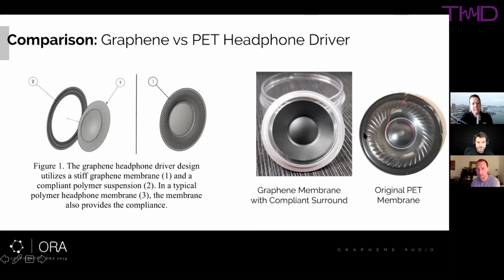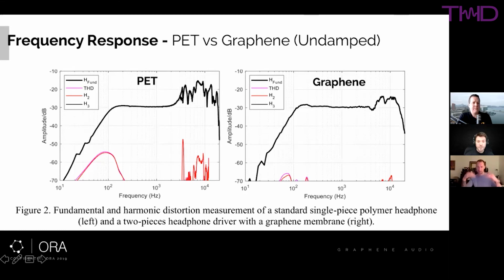So for this, we took a 50 millimeter driver that used a PET membrane and replaced it with our graphene diaphragm. And what we see is pretty remarkable, particularly in the frequency domain, because the PET membrane, in order to allow it to move, since the membrane and suspension are the same piece, the whole thing is very soft. That means you get a lot of modal energy starting at a relatively low frequency. And in these types of polymer membrane headphone drivers, a lot of the times the majority of the high frequencies is almost assembled out of these high density modal resonances, loudspeaker breakups that are so clustered that they give almost the impression of a smooth high frequency response, but it's actually a lot of clustered peaks and dips. And there's an associated harmonic and intermodulation distortion that happens with these breakup resonances.